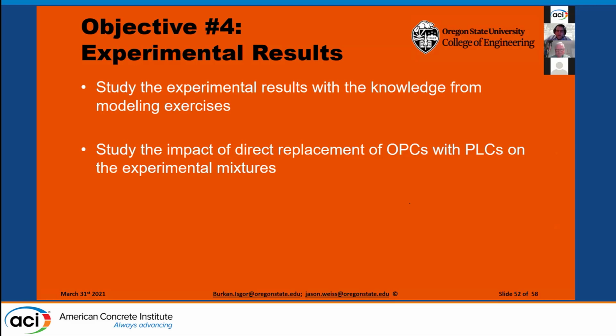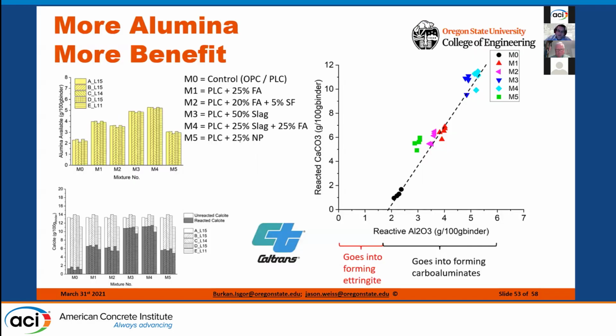So we really wanted to do some work, and we've been doing a lot of work. A report is going to be coming out in the next 3 months or so, where we've really compared about 80 different mixtures looking at OPCs and PLCs together. But the basic thing that I just wanted to mention is, again, when you start adding alumina into these systems, you get more benefit because you're reacting with more of the limestone and more of the calcite that's in the system.